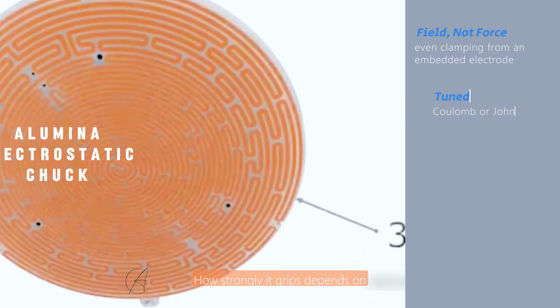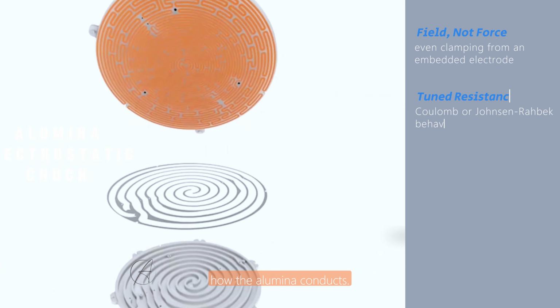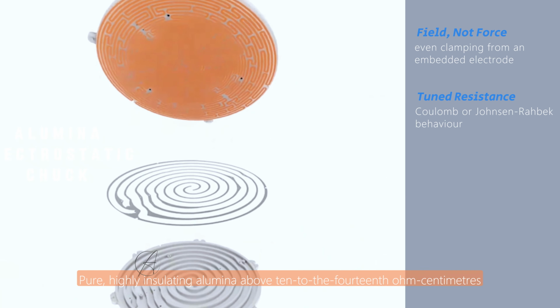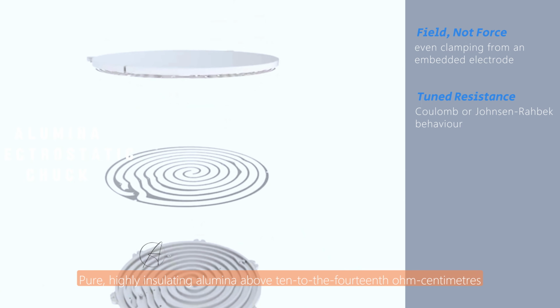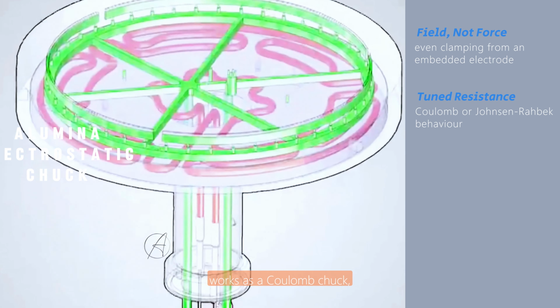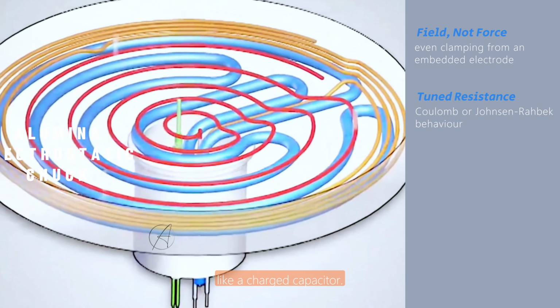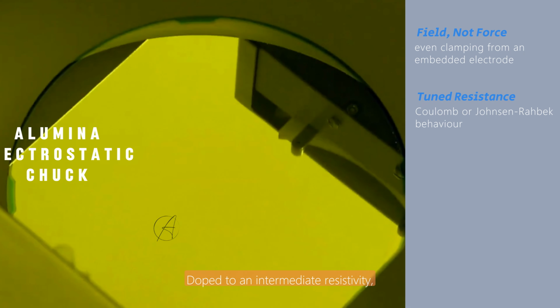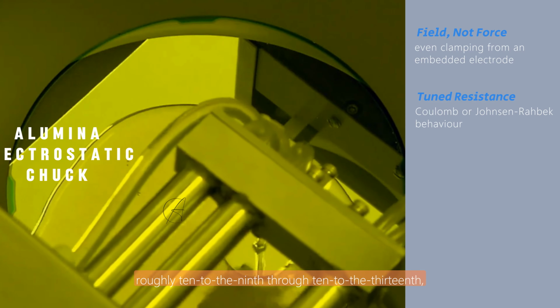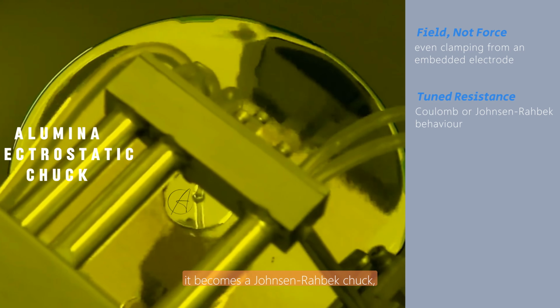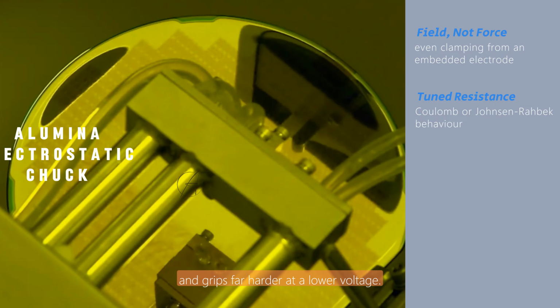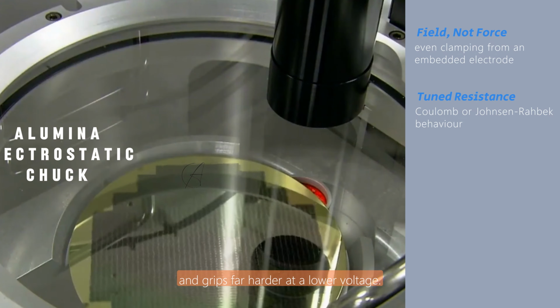How strongly it grips depends on how the alumina conducts. Pure, highly insulating alumina above 10^14 ohm-centimeters works as a Coulomb chuck, like a charged capacitor. Doped to an intermediate resistivity, roughly 10^9 through 10^13, it becomes a Johnsen-Rahbek chuck, where charge gathers right at the contact line and grips far harder at a lower voltage.